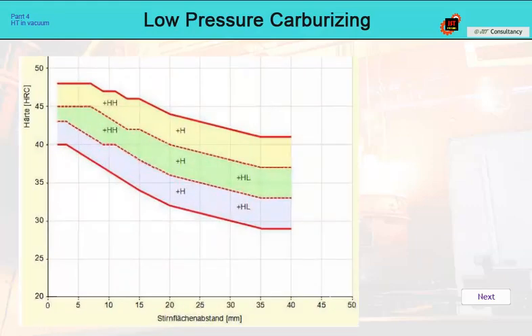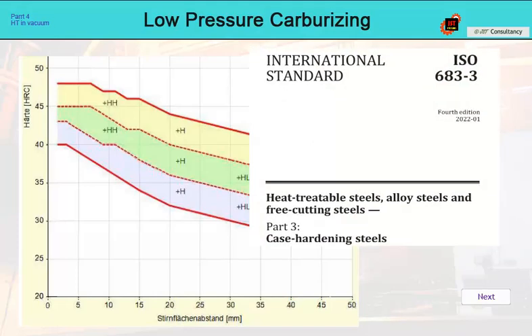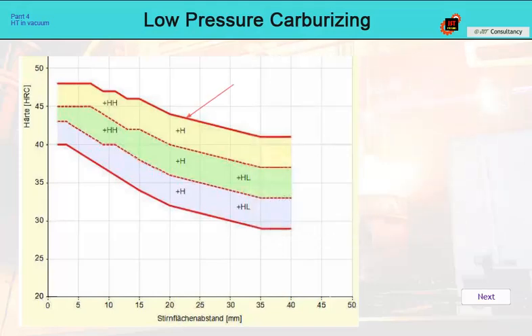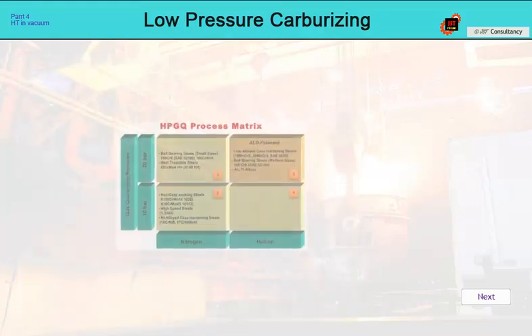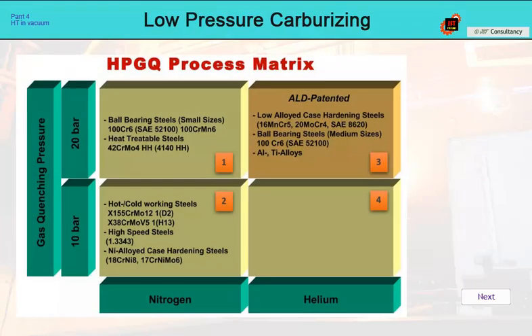Each steel has a chemical composition within a certain tolerance band for each alloy. According to the standard, for example ISO 683 Part 3, hardenability zones are defined for each steel. Therefore, in order to have stable results, we must be in the upper range of alloying. Under optimal conditions in this band, the steel will be hardenable in a gas stream, but as soon as the chemical composition corresponds to the lower hardenability range, we will not be able to quench this steel in nitrogen.